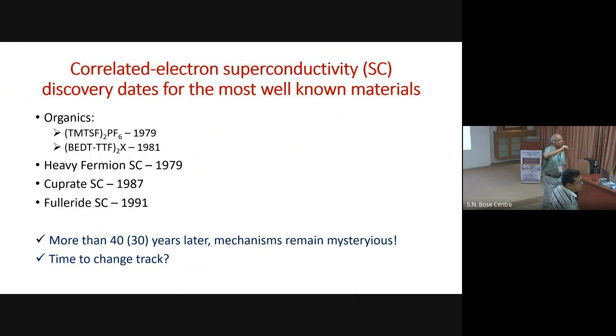If you have only 0.1 or 0.2 holes in the oxygen, then the t_pp becomes irrelevant. The oxygen hole will go to the copper; the hole moves to the oxygen. It will go through that, and therefore the intra-ladder coupling dominates. It's a population thing, it's not the hopping integral parameter.